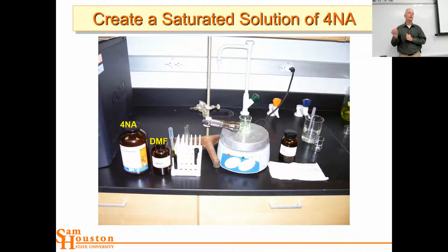One way to favor nucleation is to mix or create some sort of vibration in the solution, like scratching the side of the flask. These little vibrational waves go through the solution, and they force these molecules together, and you can get rapid nucleation. You remember doing that in organic chemistry. You recrystallize, and then you scratch the side of the flask to cause it to crash out of solution, and you'll see lots of crystals form. But if you don't scratch the flask, if you drop in a seed crystal and leave it alone, you can get large crystals to grow.